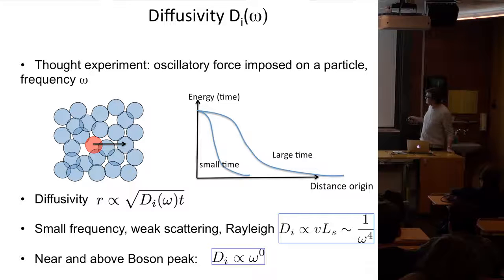Imagine you have a system. You take one particle, this particle in red, and you start to shake it at one given frequency, omega. If you do that, you will start to put energy into your system, and on long times, this energy is going to be diffusive. That would behave like a Gaussian. So what you can define is a diffusion constant that enters in this relationship: R goes like the square root of this diffusion constant times the time. If you could do an experiment like that, you could measure a diffusion constant at a given frequency omega, and that's what's called the diffusivity.